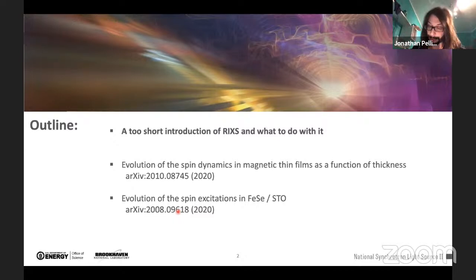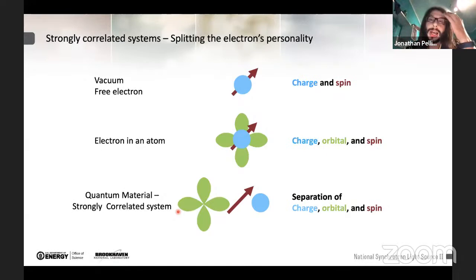So I will start with a slide just to tell you that in a strongly correlated electron system, the electron has a different personality. If we take the electron in vacuum, it has a charge and it has a spin. When we place an electron inside an atom, it also acquires an orbital momentum. And what is extremely interesting is that when we place electrons into a strongly correlated system and we allow them to interact, these 3 degrees of freedom can actually separate and give rise to a pretty interesting class of phenomena.